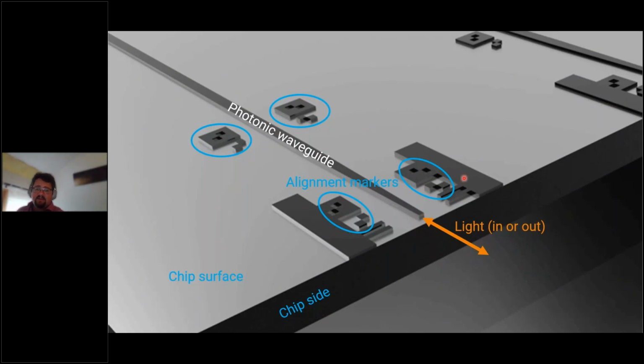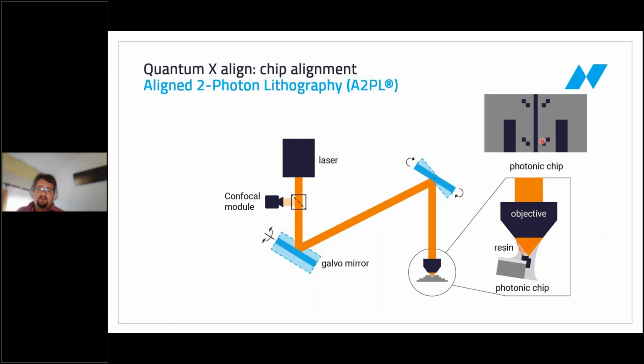And for this, you need to measure very precisely the position and the angle, because otherwise, if you print in here a lens and it's a few degrees off, then the beam will point in the wrong direction. This won't work anymore. So we have implemented this in the Quantum X Align, and we call it aligned two-photon lithography. And the sketch of the functionality here is basically the same, except for this addition here. So what we're doing now is we're using the laser, the galvo mirrors, the focusing optics and everything. We use it to scan the surface at an intensity that's below the polymerization threshold. And we're looking at the light that gets back scattered and then enters this confocal module detector.